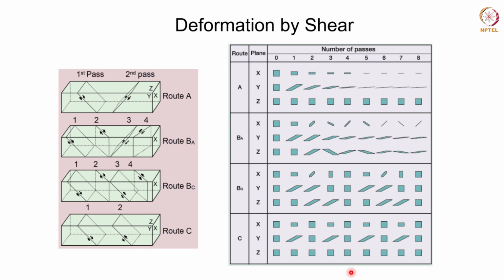Right, so this is how, with the help of this particular diagram, you can see how the shear deformation leads to accumulation of large strain in the material, and this will actually lead to refinement in the grain size. In order to understand how exactly the grain refinement occurs, apart from the physical picture that this diagram depicts, you will also have to look at the dislocation mechanisms. If you remember, I had said that dynamic recrystallization which occurs in the material can play a very important role in the severe plastic deformation process. So we'll have to look at how this particular phenomenon, dynamic recrystallization, plays a role here in refining the grain size in severe plastic deformation.